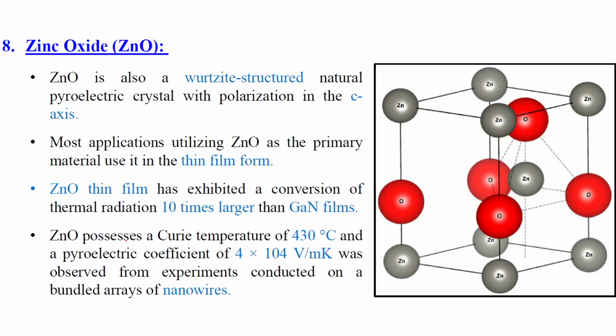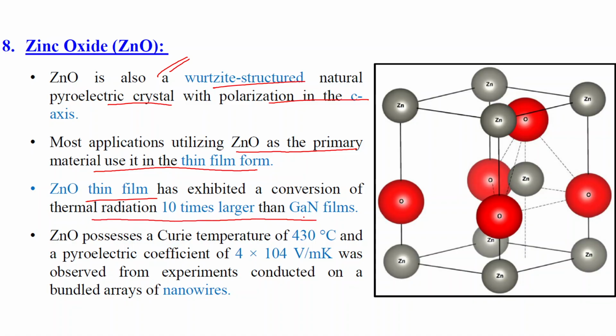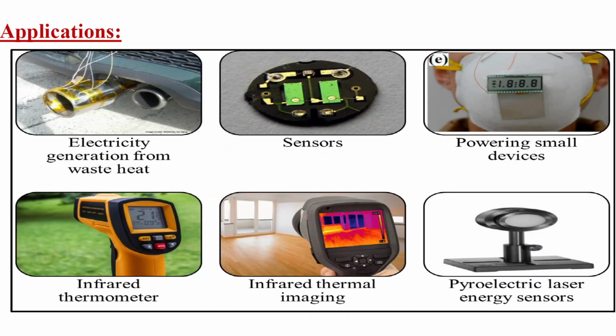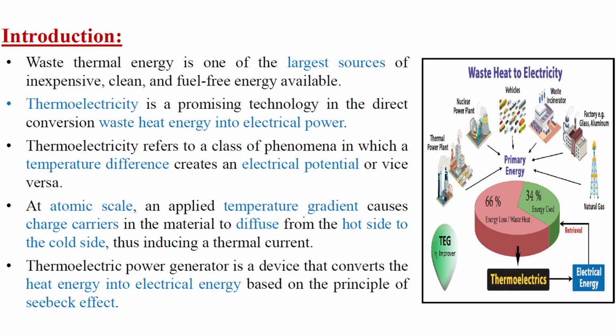Okay. Then zinc oxide, it is also quite famous. It is a wurtzite structure, natural pyroelectric crystal with polarization in the C axis. Most applications utilizing zinc oxide as the primary material use it in the thin film form. So it is also an advantage. It can be easily used in a thin film form. Zinc oxide thin film has exhibited a conversion of thermal radiation 10 times larger than gallium nitride. Okay. So these are some of the applications of pyroelectric nanogenerators, that is electricity generation from waste heat, then sensors, powering small devices, infrared thermometers, infrared thermal imaging.